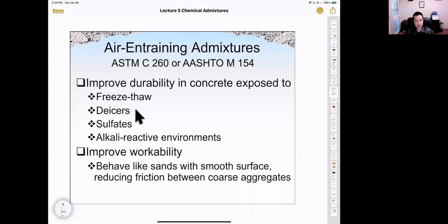So air entraining agent can improve durability to resist freeze-thaw damage, de-icing solution, and sulfate attack, which we discussed before, the formation of ettringite after concrete hardens. ASR, which is alkali silica reaction, is another type of chemical attack in concrete.